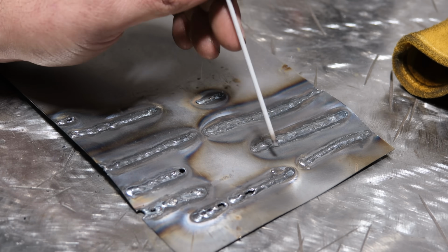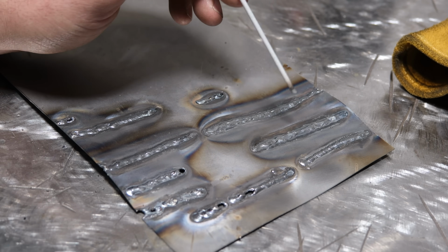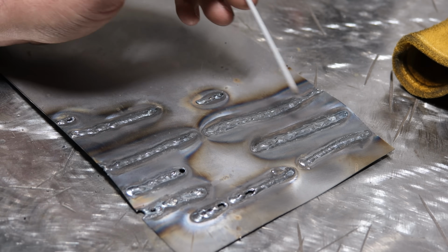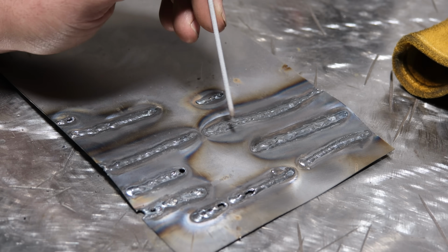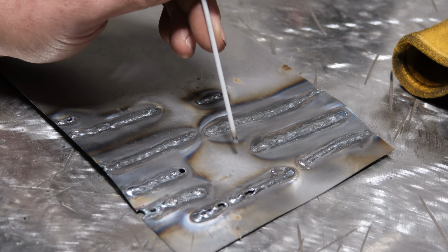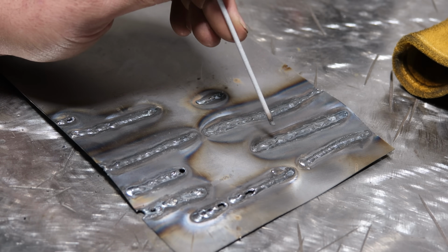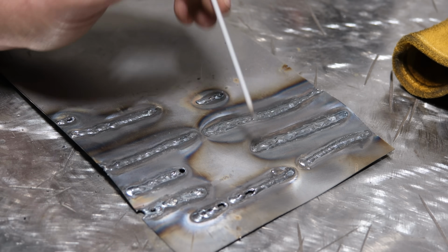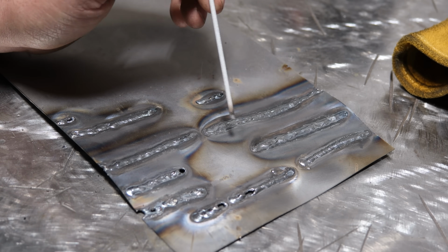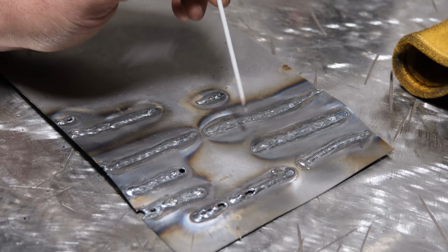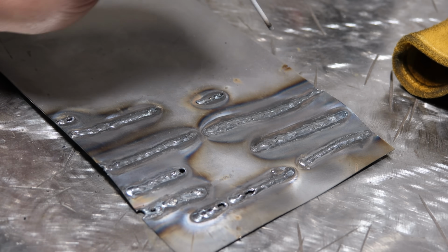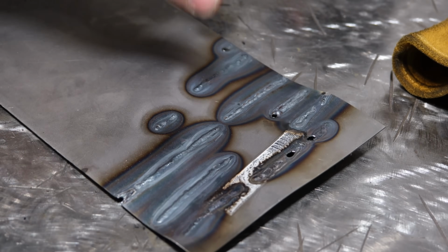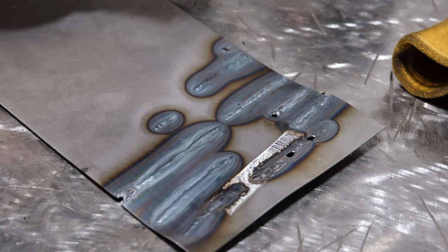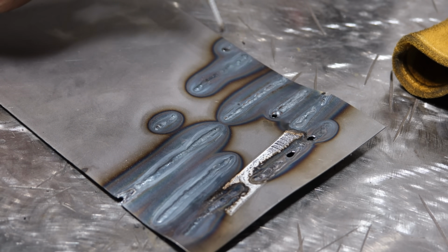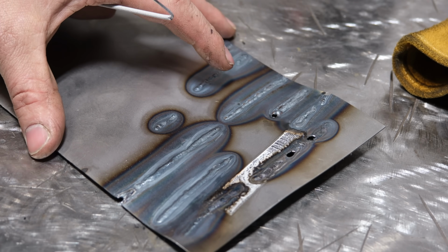Now, based on my prior experience with welding thin material together, I know that what appears hot on here is probably just the right amount of amperage to weld two pieces together, because it will take more heat. So I knew the fact I could even run a bead with any rod on this was pretty good, and that I would be able to weld two pieces together fairly easily, penetration-wise, all the way through. And that's what you're going to expect. There is no such thing as low penetration on this thin a material.